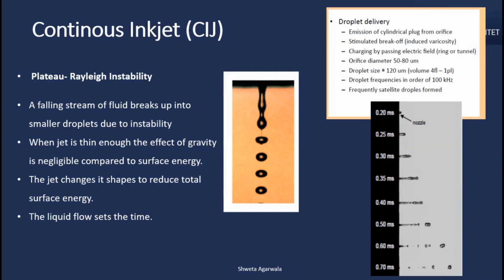What basically it means is that when you have a big stream of any liquid flowing down, it is quite unstable because of its weight and under the force of gravity. So it needs to break down into smaller droplets and take spherical shapes so that it stabilizes and has the least energy, which is favored by nature. This is a natural phenomenon: if you have any big stream of any liquid, and it's not just for water, it will tend to stabilize itself by segregating into smaller and smaller droplets. And if you observe them under a microscope, you will see that all these droplets, again, that comes from the rheological properties of the material.